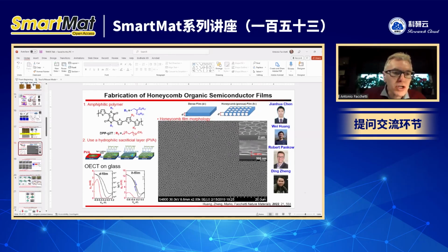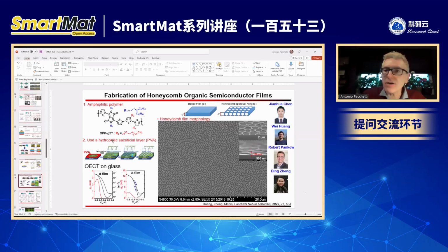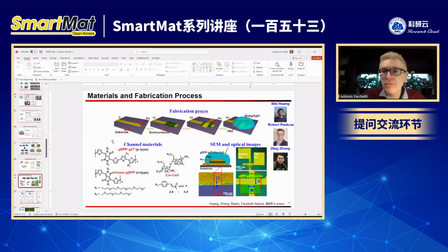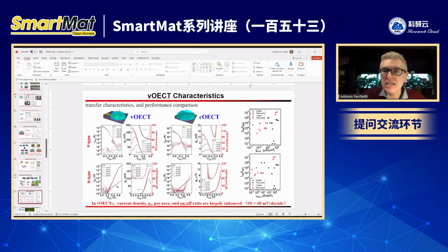If you go to the vertical transistors, the hysteresis disappears. We don't see any hysteresis. They're very fast devices, incredibly fast. We still don't understand a lot of aspects. We don't understand how the ion can penetrate. You have only 100 nanometer, and they have to penetrate 50, 100 micron.